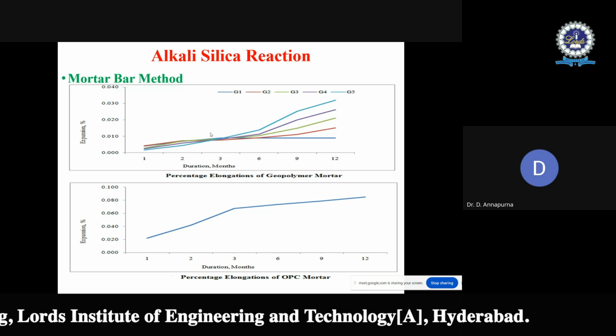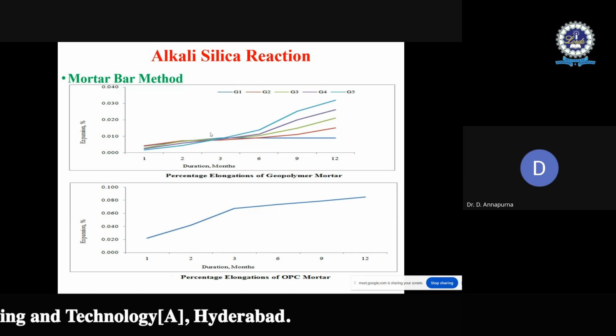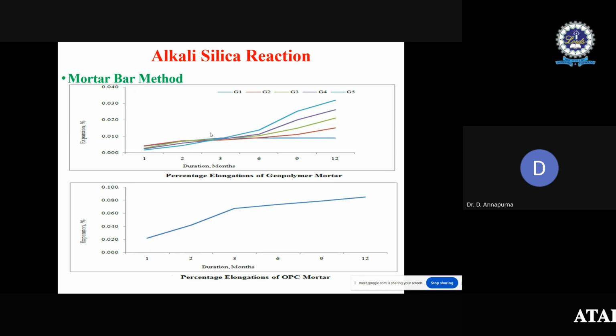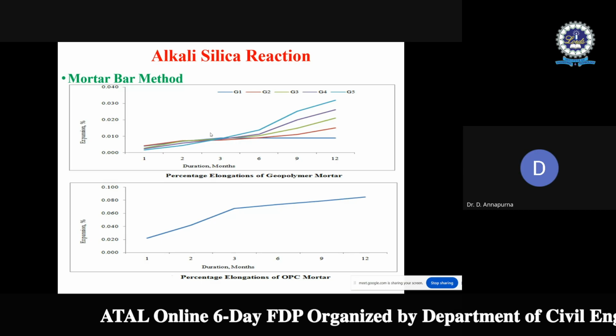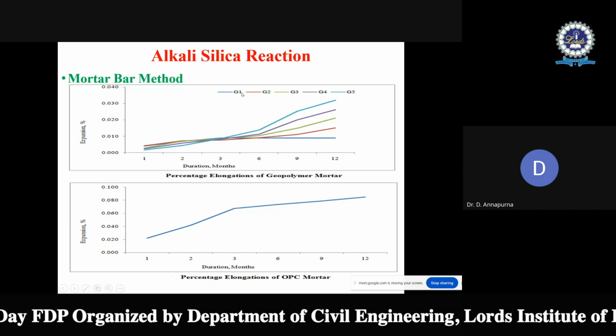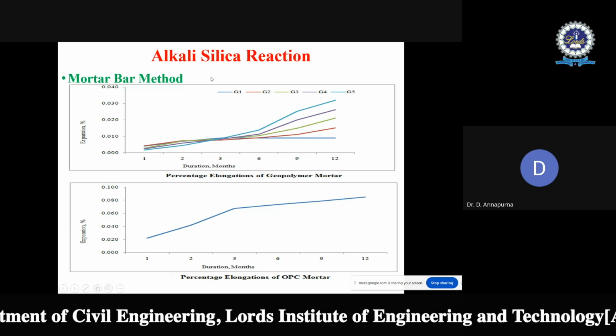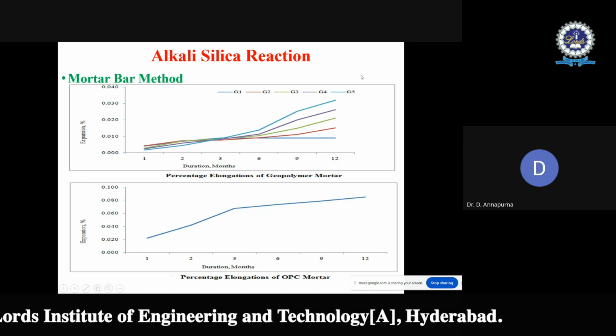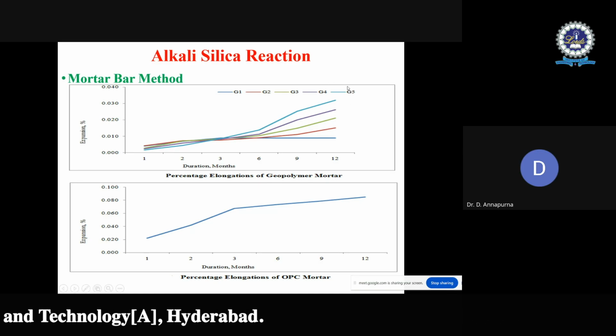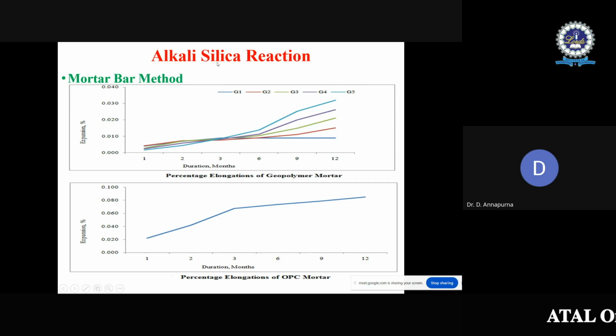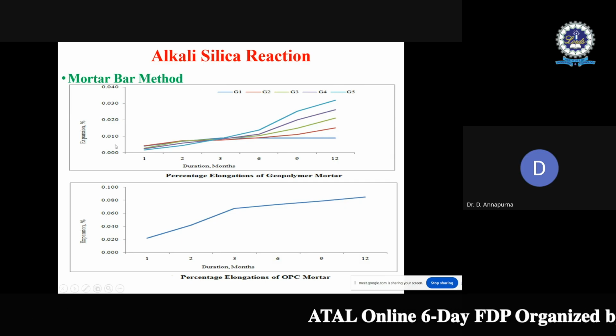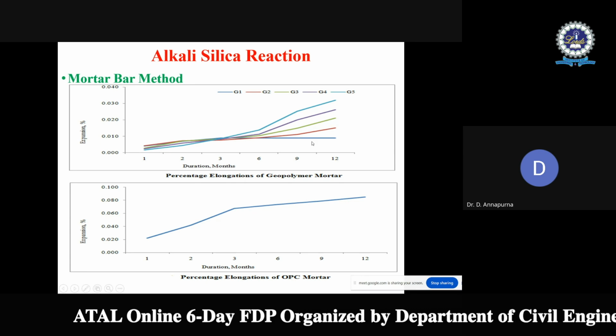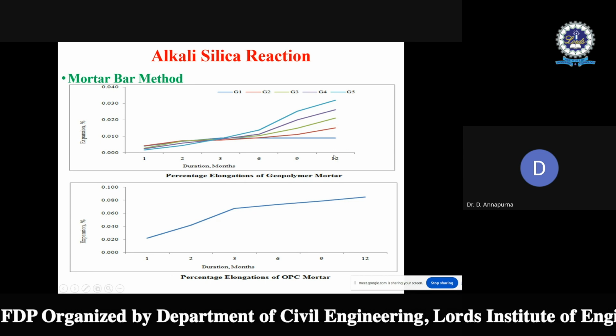To check the alkali silica reaction, the type of aggregate considered here is quartzite, which has reactive silica. That aggregate is added in the preparation of geopolymer mortar. To prepare the geopolymer mortar, 10% of GGBS is added to 90% of fly ash, up to 50% of GGBS and 50% of fly ash. The same compositions are considered to prepare the mortar bars. Percentage elongations are calculated after 12 months, that means this test is conducted up to 1 year.